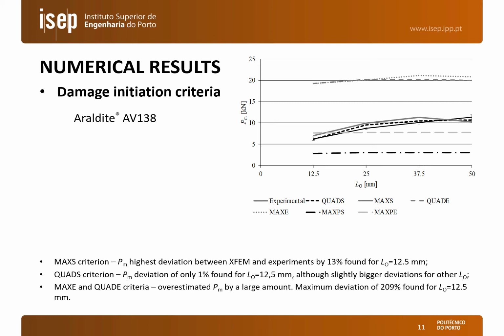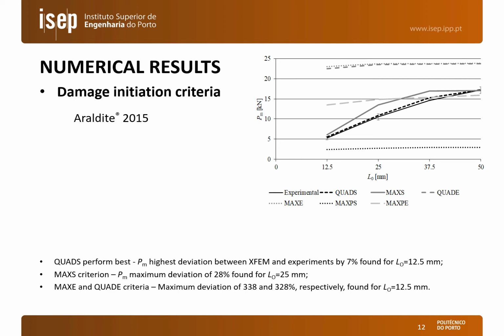On the other hand, the other criteria did not show to be so suitable, with a maximum deviation, for example, for the MAXE and QUADE criteria of over 200%. Here we can see the same analysis for the Araldite 2015. Once again, the best results were found for the quad S and max S criteria, but here the quad S criteria gives better results, and the highest deviation for this criteria was 7%, for an overlap length of 12.5 millimeters.